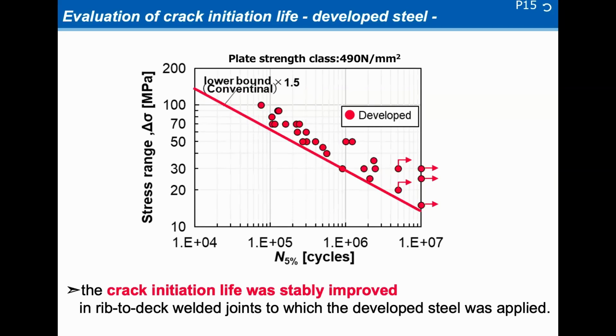Finally, this chart shows the S-N diagram when the developed steel is applied. The initiation life of the developed steel is not less than 1.5 times the lower bound of conventional steel. So the crack initiation life was stably improved in rib-to-deck welded joints to which the developed steel was applied.